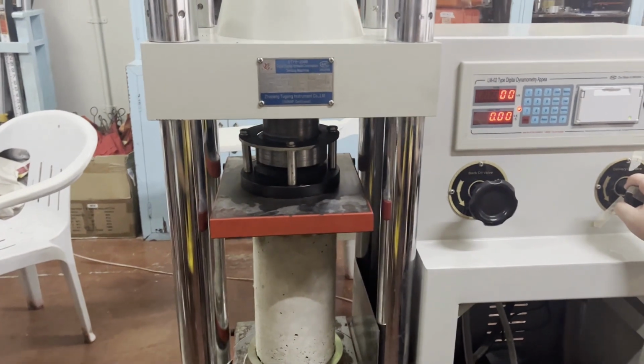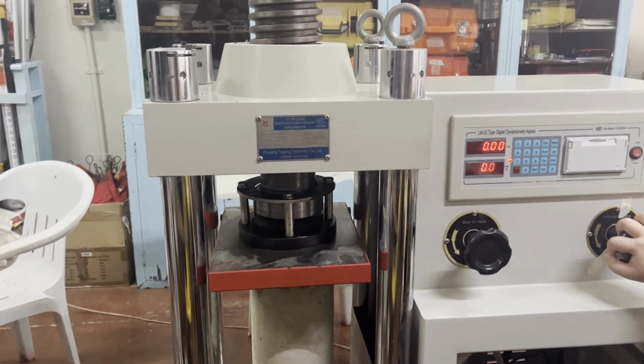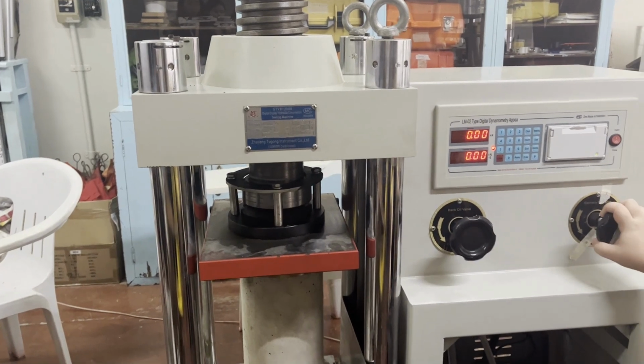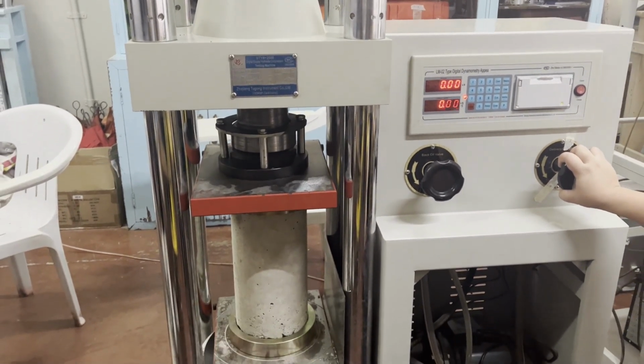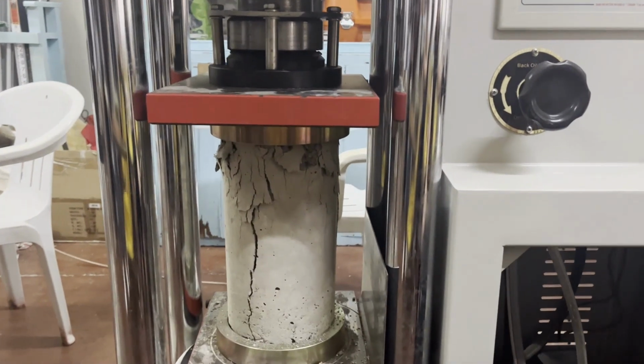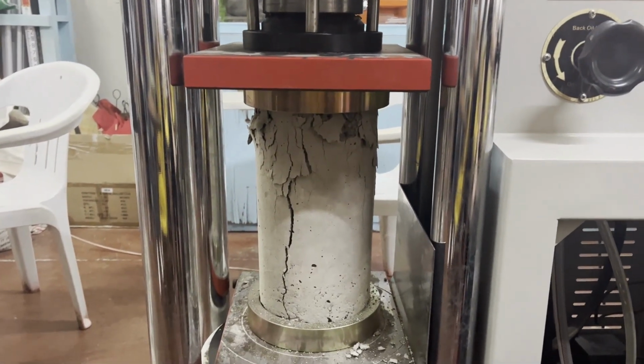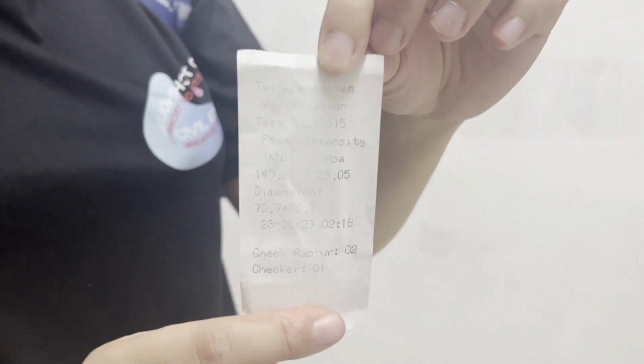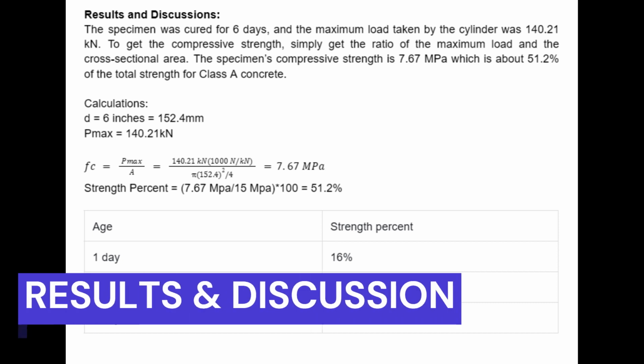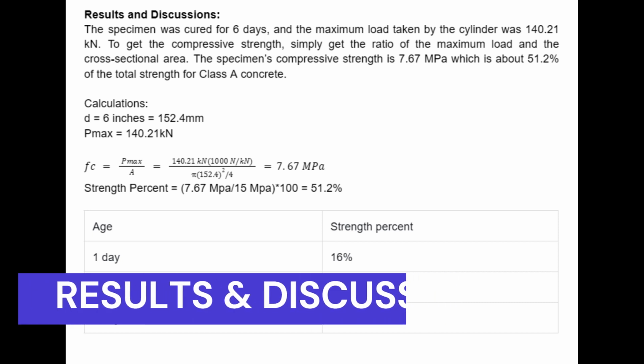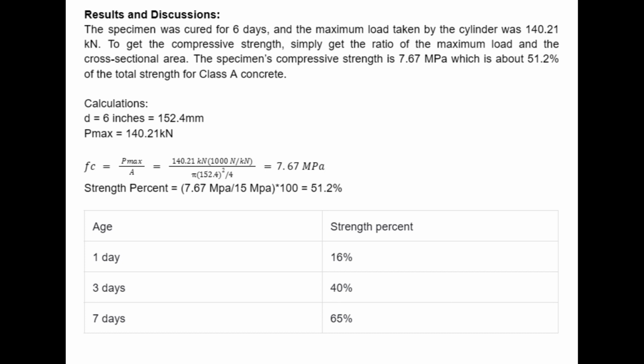Fifth, apply the load continuously and uniformly without shock at 315 kN per minute and continue the loading until the specimen fails. Lastly, record the maximum load taken. Results and discussions. The specimen was cured for 6 days, and the maximum load taken by the cylinder was 140.21 kilonewtons. To get the compressive strength, simply get the ratio of the maximum load and the cross-sectional area.